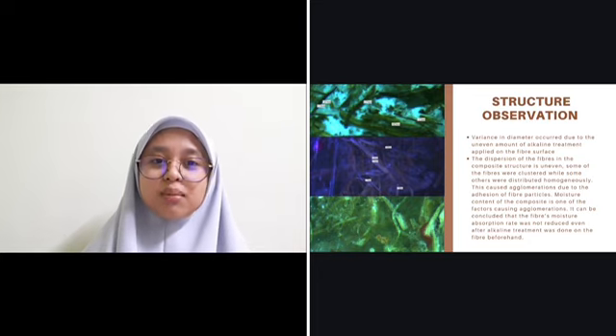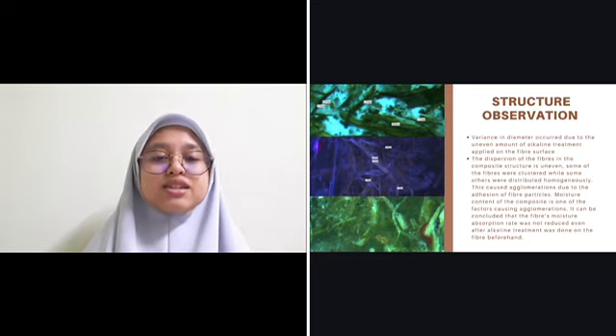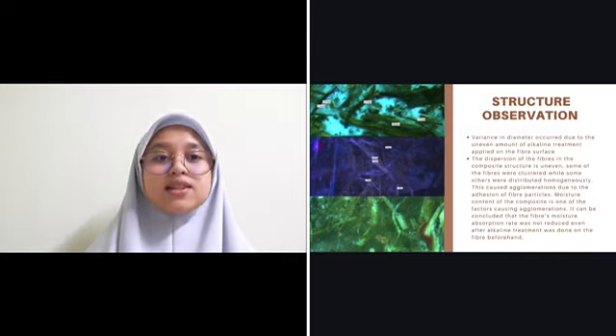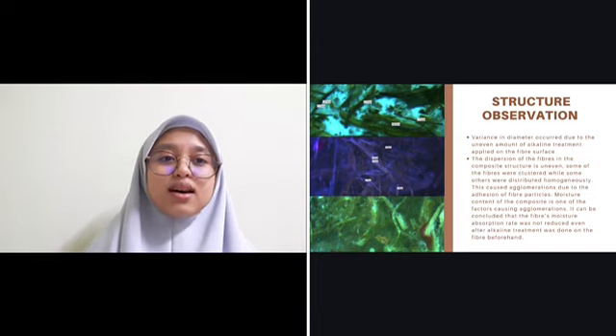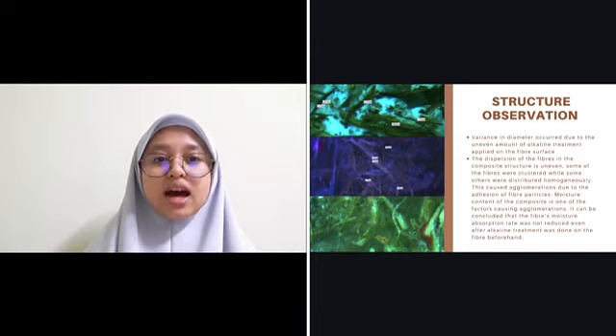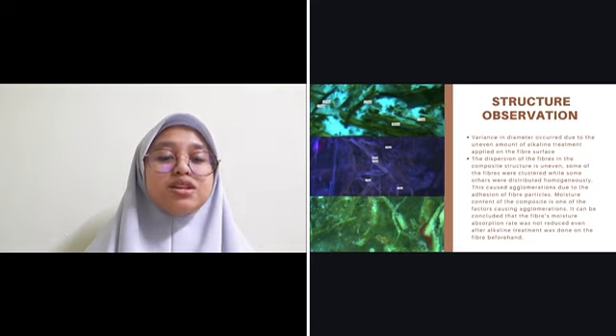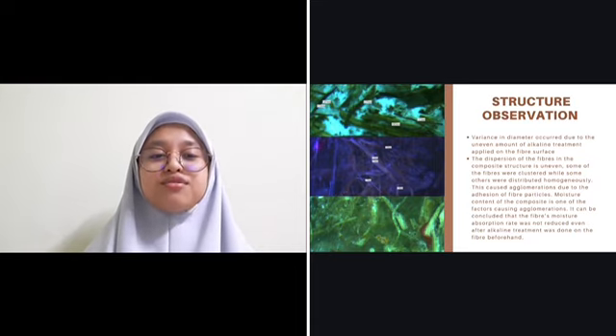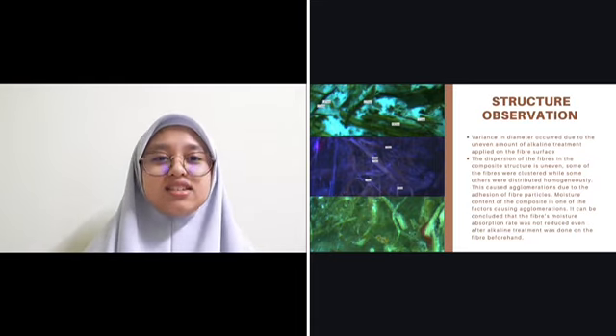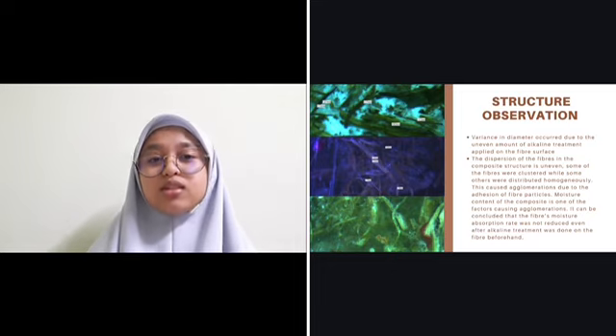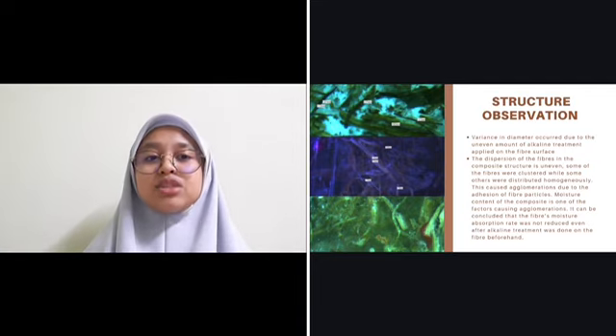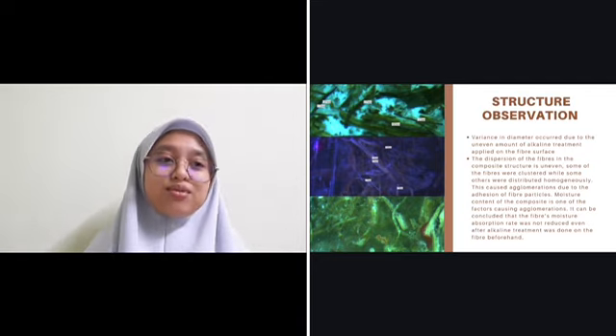The partial homogeneity of fibers in a certain part of the composite structure caused agglomerations due to the adhesion of fiber particles. One of the factors causing agglomerations is the moisture content of the composite. Considering the factor, it can be concluded that the fibers' moisture absorption rate was not reduced even after alkaline treatment was done on the fiber beforehand.